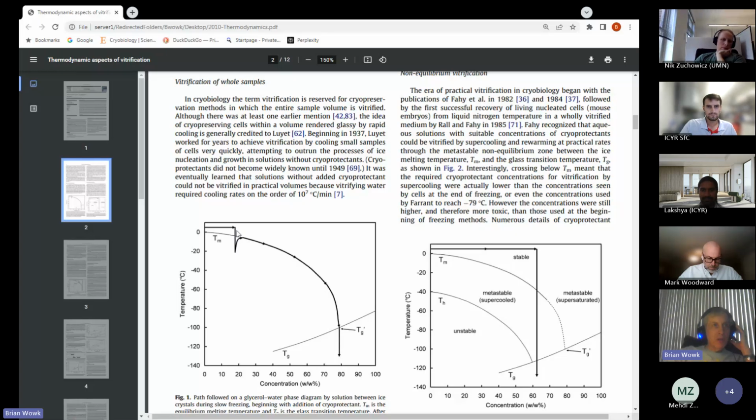Typically in a freezing protocol, you cool on the order of 1 degree a minute, and then temperature will actually go below the freezing point, aka the melting point, because typically solutions, even pure water itself, will supercool before it actually freezes. So it'll start going down some distance, and then eventually an ice crystal will nucleate, and then the heat will be released, and the temperature will pop back up to become equal to the melting temperature.